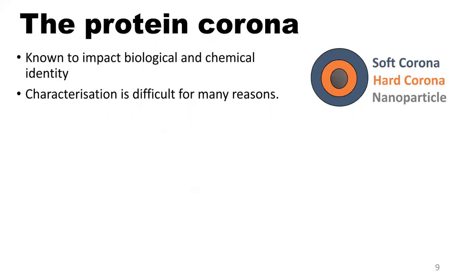Characterization of the protein corona is then difficult for many different reasons. If you want to characterize the soft, loosely bound corona, you'd first want to remove any excess unbound protein. And the easiest way to do this would be simply to centrifuge the nanoparticles and resuspend the pellet. But by doing this, you also throw off this corona in the process. So maybe we should analyze the hard corona instead. It's much more strongly bound, so maybe this will be really easy, right?